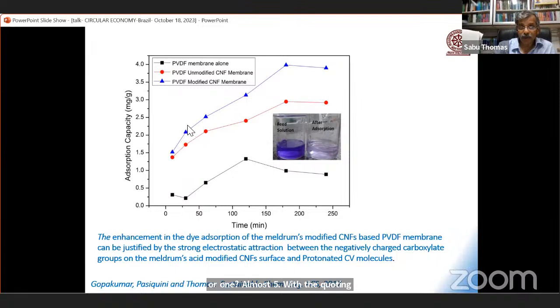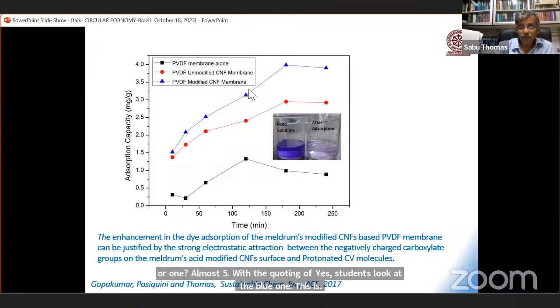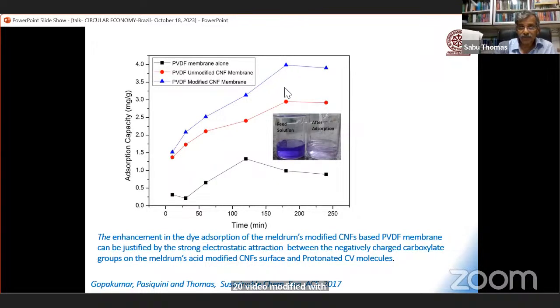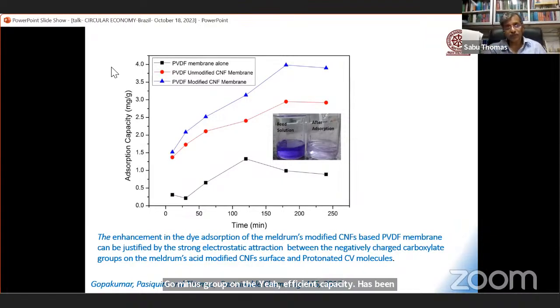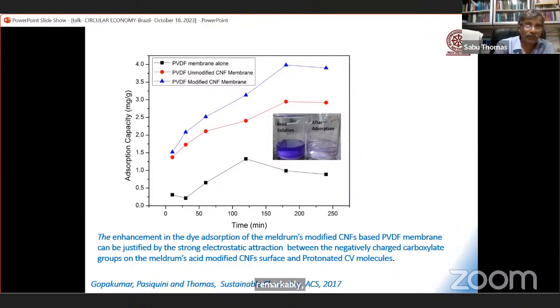Yes, students, look at the blue one. This is PVDF modified with chemically modified nanocellulose with the CO minus. Once you put the CO minus group on the nanocellulose on the surface of the filter, the adsorption capacity has been remarkably increased. Now the value is 4. So this is a remarkable increase in the capacity. Interesting. This is the impure water, and this is the purified water.